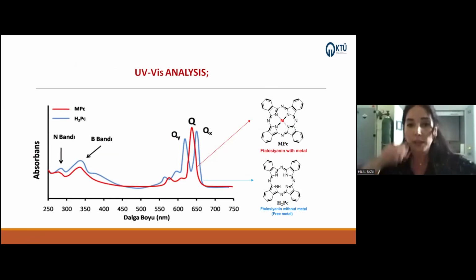And how do we determine whether the metal ion has coordinated to the central cavity of the phthalocyanine molecule? Of course, the UV-visible spectroscopic technique. The UV absorption spectra of metal and non-metal phthalocyanine molecules are shown here in the figure. Non-metal phthalocyanine exhibits a split Q band appearing as a double peak. The blue line represents this molecule without metal. However, when a metal atom occupies the central cavity, the phthalocyanines show a single Q band. The red line represents these molecules with metal. In this way, we can determine whether the metal has successfully coordinated to the synthesized phthalocyanine molecule using the UV-visible spectroscopic technique.